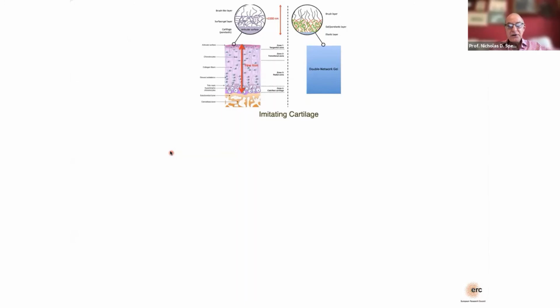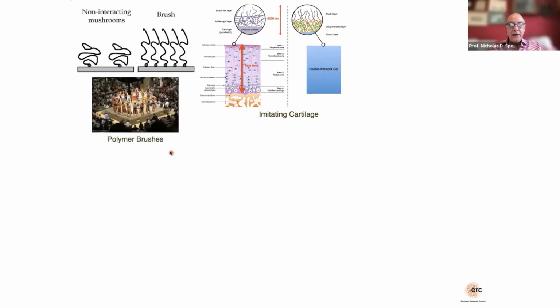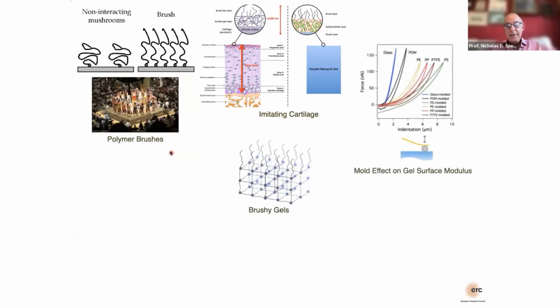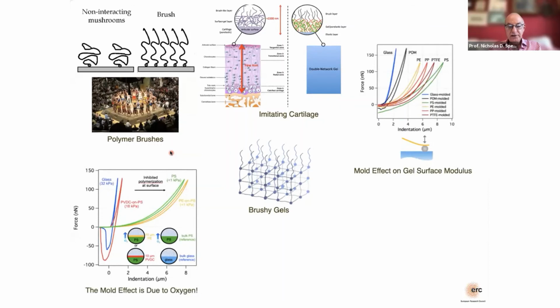I started off telling you about imitating cartilage using hydrogels and dangling chains in order to imitate the behavior of cartilage. I showed you one way in which we've done this, a physical way using a mold effect. We've done many other approaches using chemical ways of functionalizing double network gels, and you can find that pretty easily in the literature. I explained what polymer brushes were, how we think of gels, and the way the mold can affect the surface modulus of hydrogels and also the friction.